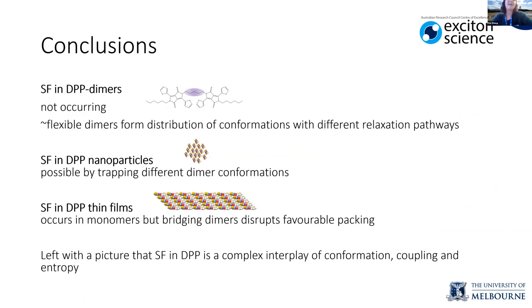So just to go over the main conclusions, I didn't see any singlet fission in the DPP dimers, and I think that that's because we have all of these different conformations, and that if anything, they'll take a charge transfer pathway compared to this option of singlet fission. And in DPP nanoparticles, I could see fission, but only when you trap these particular conformations. So that's obviously something that I'm focusing on the last couple of months, trying to understand why it is that those particular conformations are important.